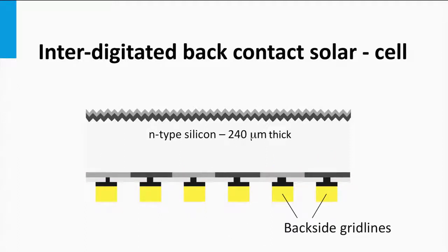The semiconductor-metal interface is kept as small as possible to reduce the unwelcome recombination at this defect-rich interface. Another advantage is that the cross-section of the metal fingers can be made much larger to reduce the resistive losses of the contacts as much as possible. The fact that the contacts do not cause any shading losses at the back allows them to become larger.